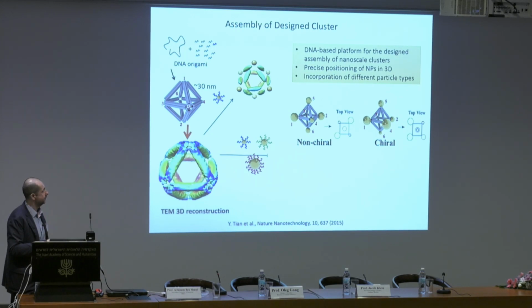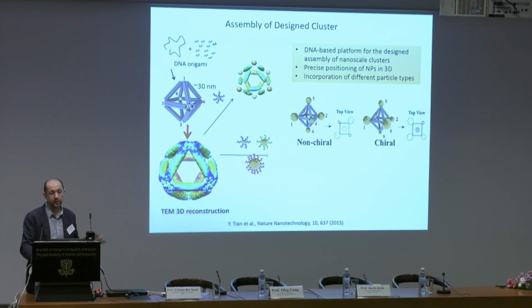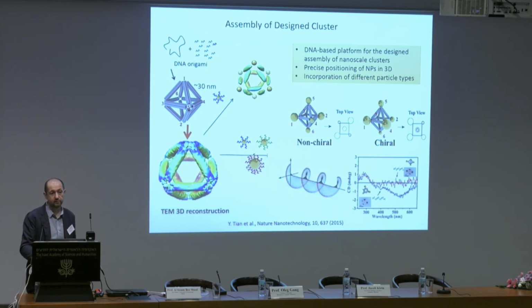In non-chiral, the particles of the same size will be on opposite vertices, and in chiral they will be on the same side. Because the particles are plasmonic, we also can check that using circular dichroism, even though the coupling is very weak because the distance is relatively large, but it's still something which we can observe.